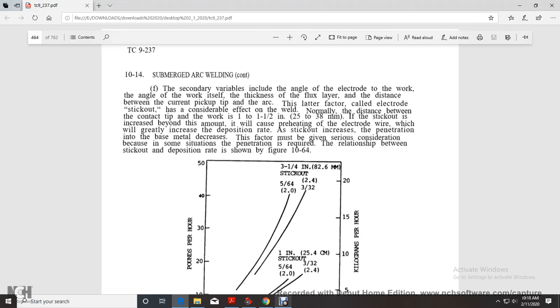Normally, the distance between the contact tip and the work is 1 to 1.5 inches of stick-out. If increased beyond this amount, it will cause preheating of the electrode wire, which will greatly increase the deposition rate, while decreasing the stick-out will increase the penetration into the base metal.